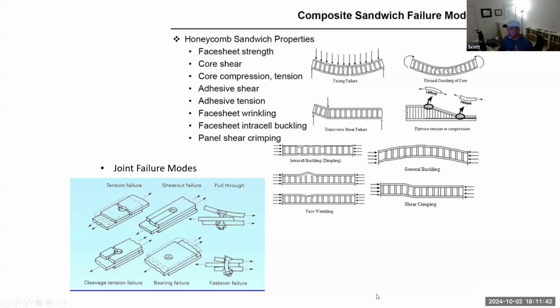A lot of these are obvious. Face sheet failure, where the face sheet ruptures. We talked about this flexural crushing of the core, so buckling of the core in the transverse direction. Transverse shear failure of the core at the ramp regions, in the curvature zones. There's a flatwise tension and compression that you've got to check for. Intracell buckling, dimpling of the face sheets. There's general overall instability of the honeycomb sandwich panel as a whole. There is shear core instability as well. And then there's face sheet wrinkling.